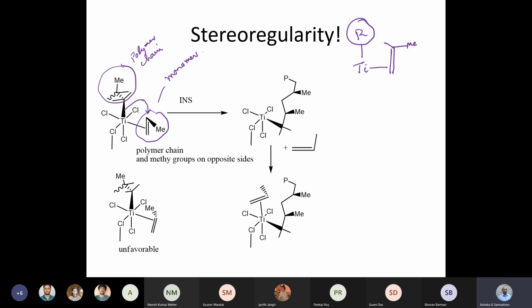So this is the large R group with a growing polymer chain. This has to move a little bit along this axis so that you end up with the formation of this species. This incoming alkene will now coordinate to the adjacent site of the titanium, and that will give you a second intermediate.